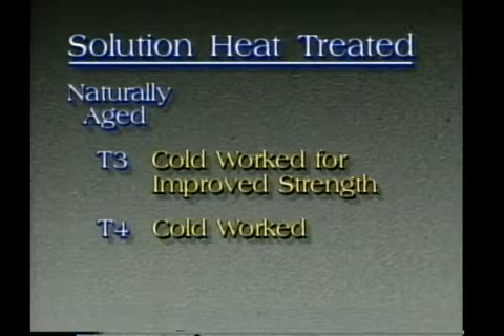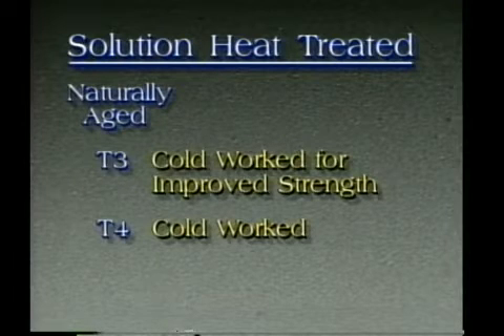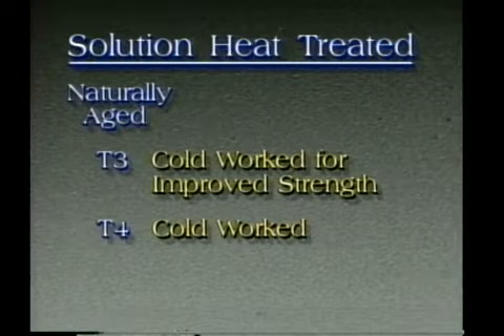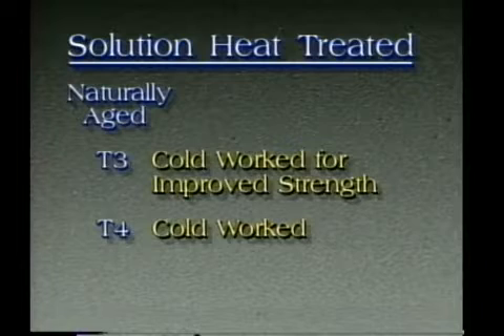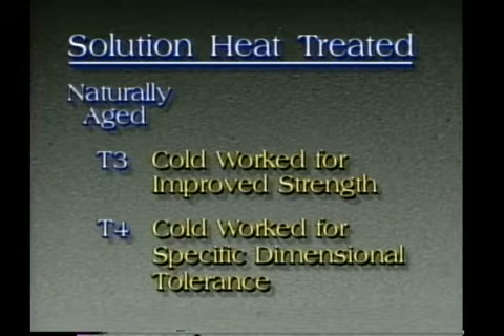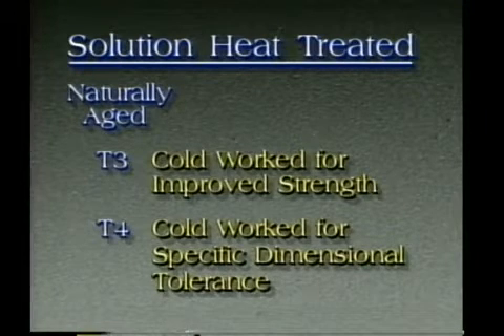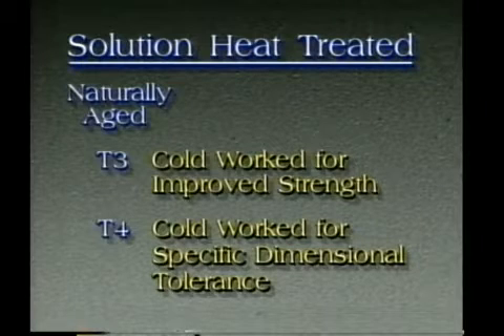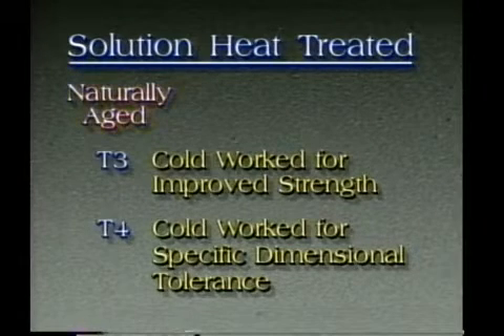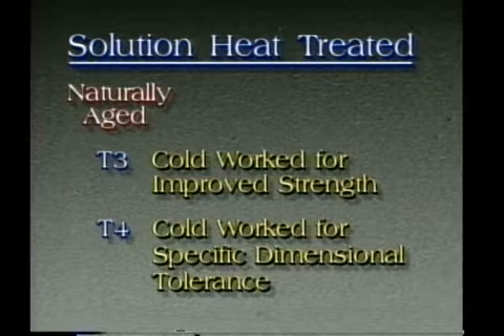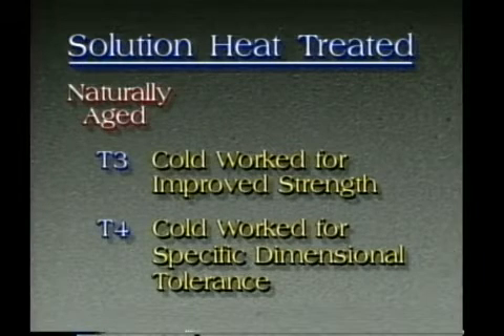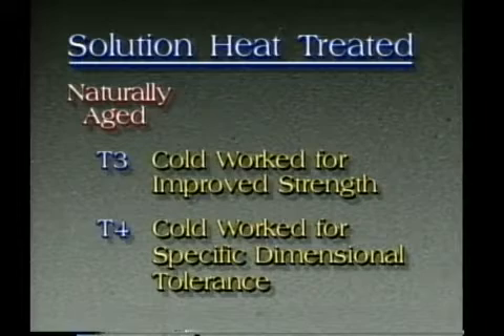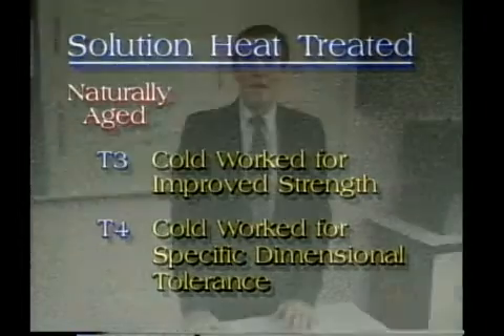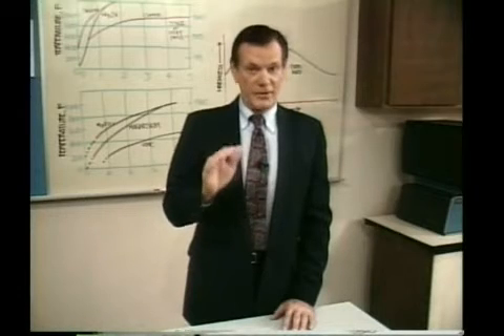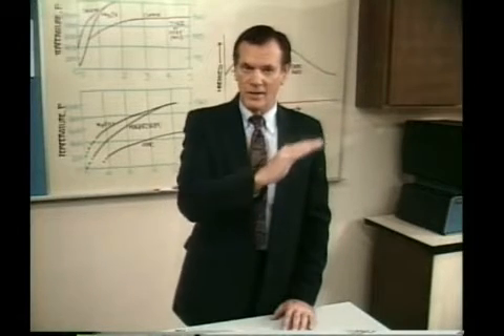The T4 temper may or may not be flattened or straightened. In the case of T4, the straightening operation is performed with the objective of achieving a specific dimensional tolerance and not for the purpose of improving properties. The T3 and T4 tempers are both naturally aged. They harden naturally at room temperature in approximately 4 days after solution heat treating and quenching. The hardening reactions occurring at room temperature cause a significant increase in strength and hardness.